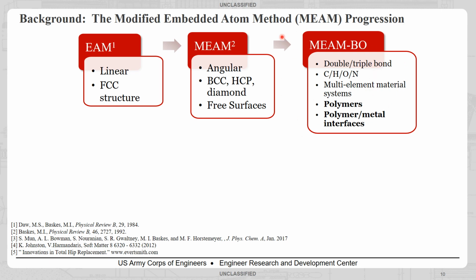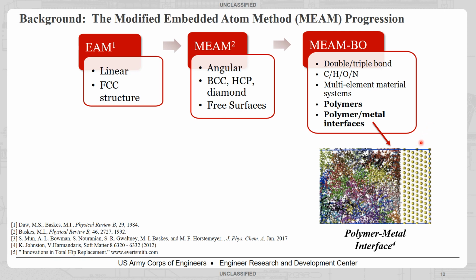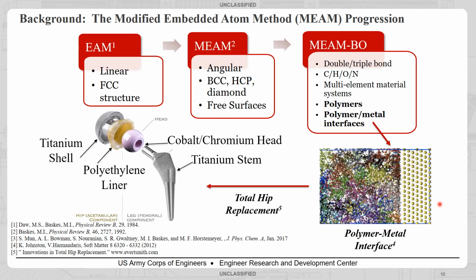And then finally, within the last few years, this bond order component has been added to look at double and triple carbon bonds, oxygen and nitrogen, graphene, materials like that. What's interesting about this is that it will allow us in the future to look at polymer metal interfaces using the same functional form between the two. So you have a much easier time of parameterizing these potentials. A lot of good metallic potentials already exist. And then we can look at these complex interactions or interfaces between polymers and metals, such as what you see here with this polyethylene liner sandwiched between these two metals.